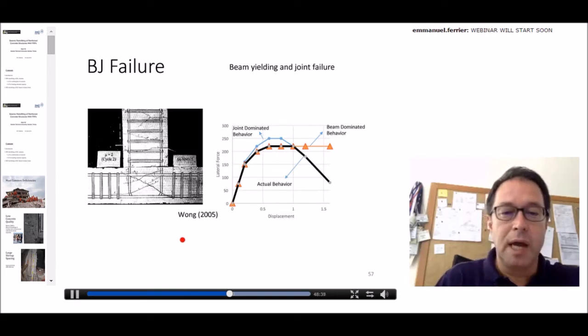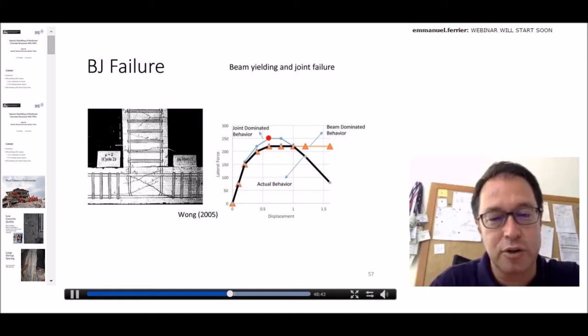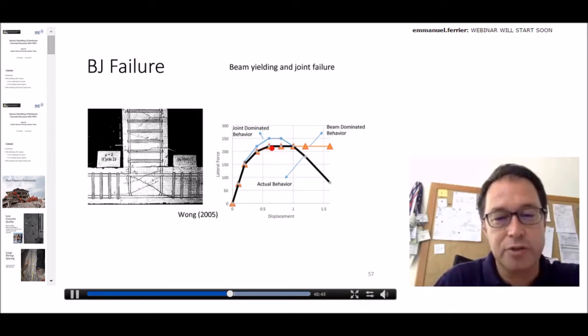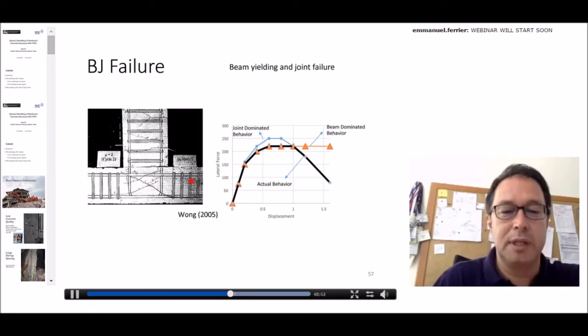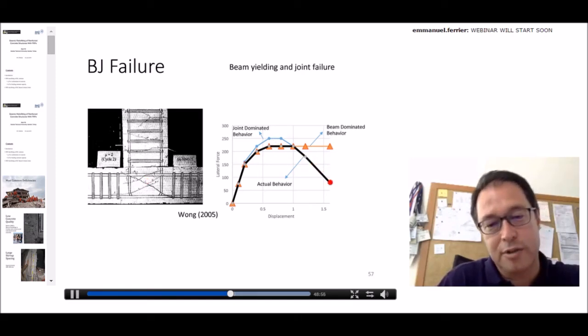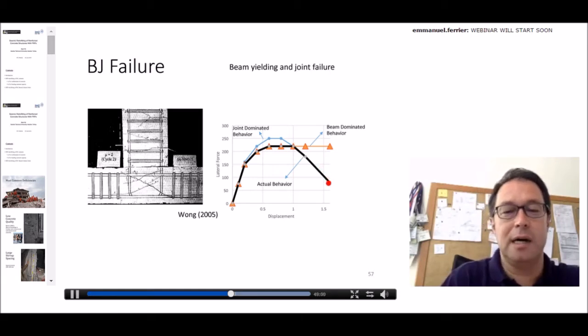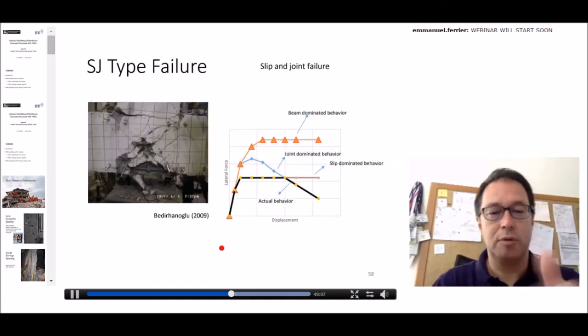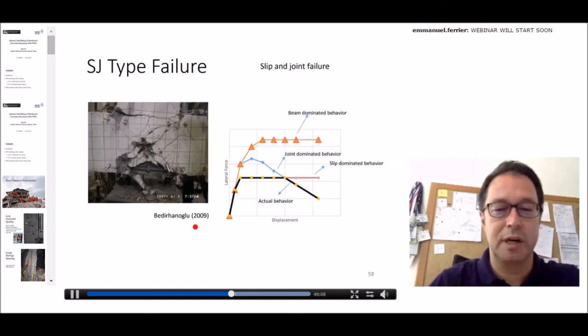And if you look at BJ-type failure, it means that our joint strength is actually higher than the beam yielding strength. However, with the yielding of the beam and the increasing deformations, the joint also fails. So we have such a failure mechanism. We have a little bit of ductility, but then because of the joint shear failure, we have a reduction in ductility. I'm going to show some test results related to all these kinds of failures.